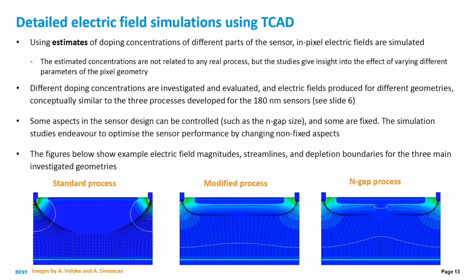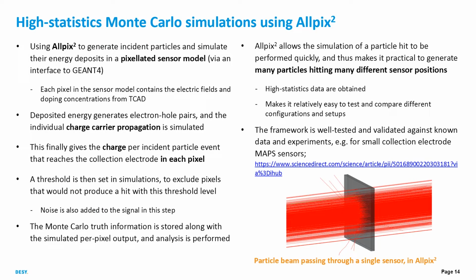Now, we take these and we input them into Allpix squared. So in Allpix squared, we can simulate energy deposits in a pixelated sensor model via Geant4, which is nice. Each pixel then contains the doping concentrations and electric fields from TCAD. The deposited energy creates electron-hole pairs, and then we simulate the individual charge carrier propagation. And then we get the charge per incident particle event that reaches a collection electrode in every pixel. Then we can set a threshold in simulations to exclude pixels that wouldn't produce a hit with a given threshold level. We also add some noise to the signal. We store the Monte Carlo truth and the simulated per pixel output and do some analysis.